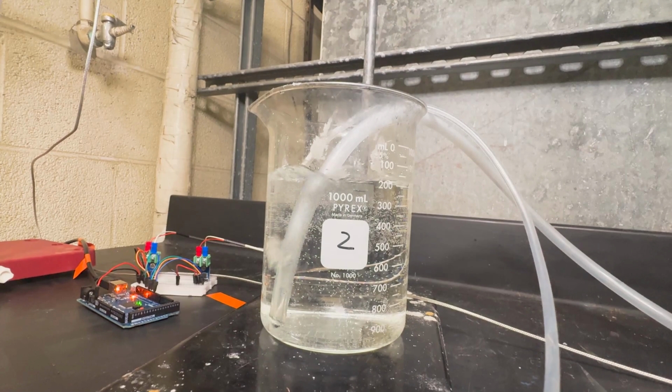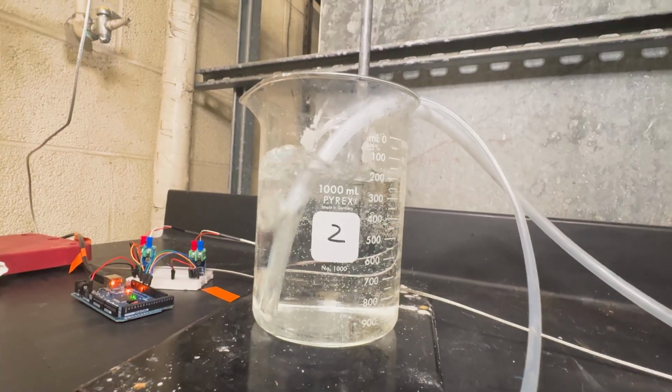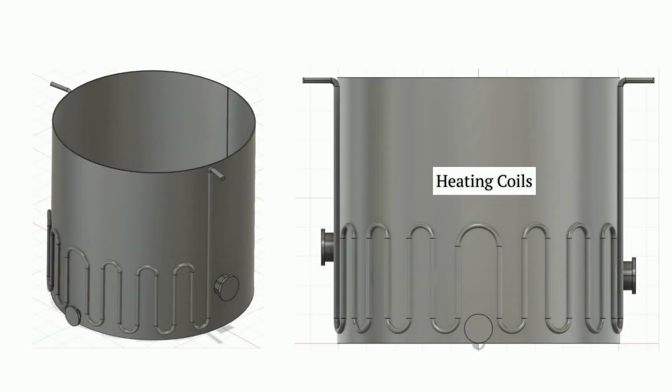We determined that the optimal pyrolysis temperature is between 500 and 550 degrees Celsius. We also learned that a specific nitrogen flow rate is required to transport the pyrolysis products out of the system. The bench scale tests also helped us optimize our cooling water flow rate and cooling water temperature. Additionally, we optimized the heat exchange area necessary to maximize the liquid oil yield.